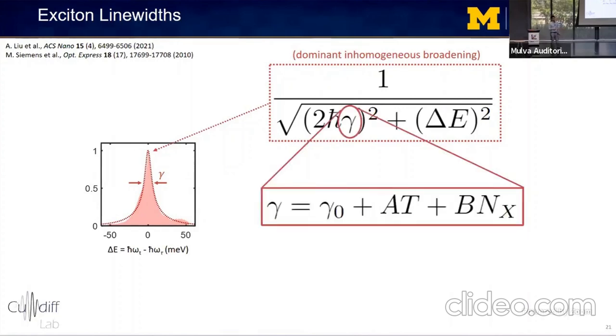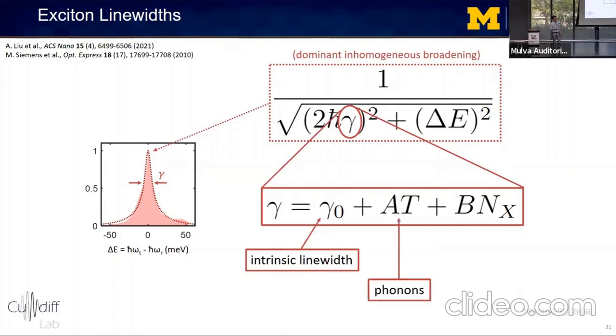So there's first the intrinsic line width gamma naught, which one can think of as the natural line width of an isolated oscillator at 0 temperature. And this is essentially limited by population relaxation. The second contribution is a linear dependence on temperature. So this is due to exciton-phonon coupling with acoustic phonon modes. And the last contribution is a dependence on exciton density. So this reflects broadening due to exciton-exciton scattering.